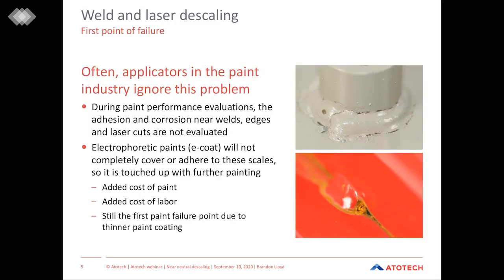So often applicators in the paint industry ignore this problem, being the poor adhesion of paint for weld and laser cut areas. During paint performance evaluations, the adhesion and corrosion near welds, edges, and laser cuts are often not evaluated or completely ignored. Electrophoretic paints, being E-coat and KTL, will not completely cover or adhere to these scales, so it is often touched up with further painting. This creates a couple of problems, because when you do this, there's of course an added cost for paint, added cost for labor, and still this is often the first point of failure due to the thinner paint coating.